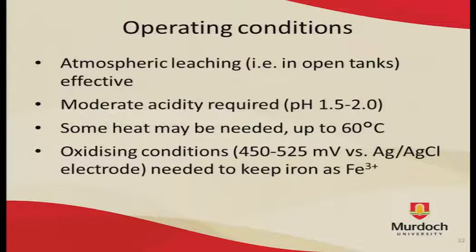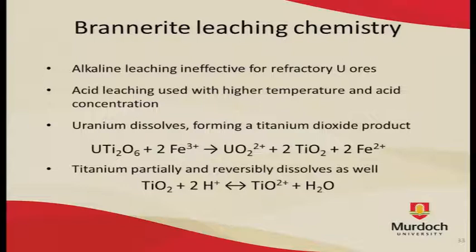Oxidants will need to be added just to keep it under relatively oxidizing conditions, just to get the uranium in solution, keep it soluble. The higher the oxidizing potential, the more iron will be present in the usable ferric state. So, now, specific to brannerite, alkaline leaching is not known to be particularly effective for it, so we're restricted to working under acidic conditions. Same sort of reagents are used, just more of them, higher reagent concentrations, and usually working at elevated temperature as well.